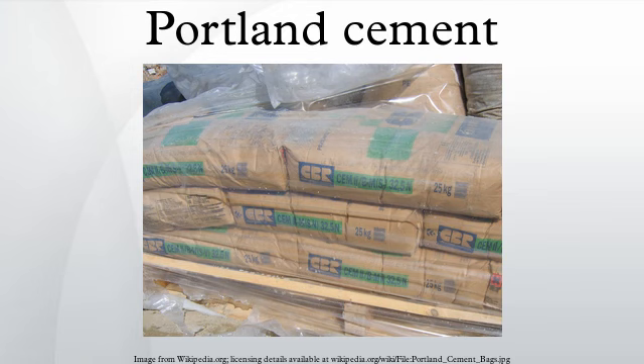Typical electrical energy consumption is of the order of 90 to 150 kWh per ton cement, equivalent to 0.09 to 0.15 kg CO2 per kg finished cement if the electricity is coal-generated. Overall, with nuclear or hydroelectric power and efficient manufacturing, CO2 generation can be reduced to 0.7 kg per kg cement, but can be twice as high. The thrust of innovation for the future is to reduce sources 1 and 2 by modification of the chemistry of cement, by the use of wastes, and by adopting more efficient processes.